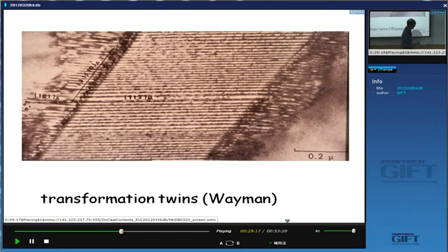So what happens is we get this tilting, but then we get plastic accommodation. This is alpha prime, gamma, and gamma. This is plastic accommodation in the austenite. So the austenite is not able to support that large shear. And that is what generates the dislocations, because then when the martensite plate becomes thicker, it absorbs those dislocations. So the dislocations that you see inside martensite are because of the plastic relaxation of the shape change.